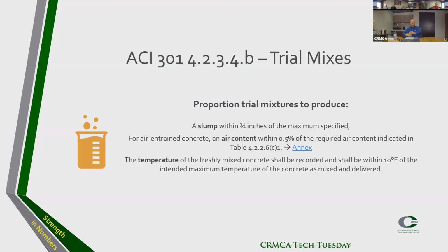Trial mixes. This is directly from ACI 301. If you do a trial mix, the slump should be within 3/4 inches of the max specified. If it's an air-entrained concrete, the air should be within 0.5% of the required air content. There's a table in the annex. And the temperature of the freshly mixed concrete should be within 10 F of the intended max temperature as mixed and delivered.